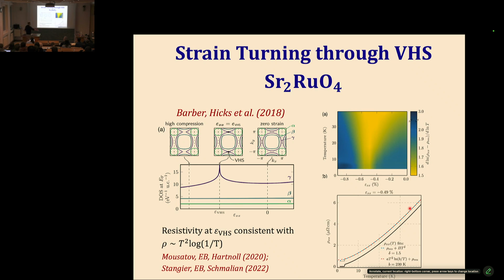And you can look at the behavior of the resistivity as a function of temperature exactly at this point, exactly at the critical value of the strain. And indeed, it can be fit to an exponent of 1.5, but it turns out that it can be fit equally well to T squared log T. And since this experiment, experiments at lower temperature have been done. The limiting factor, by the way, the reason this experiment was terminated at 3 to 4 Kelvin, is because the system is going superconducting at that temperature. Interestingly, the superconducting Tc is actually very dramatically enhanced when you approach this critical strain. But by applying a small amount of field, you can suppress Tc and actually extend this measurement down to lower temperatures.